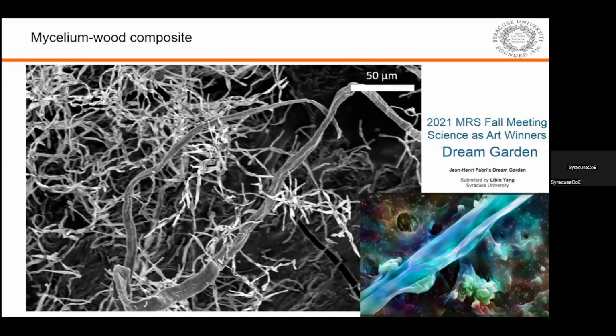And after we grow the mycelium on the petri dish, we put it together with wood fibers as the biomass. The wood fiber can be coconut fiber, or stalk or straw from corn after harvesting. We use a blender to convert those fibers into small pieces and grow mycelium together. Here's the microscopic image. The thin fibers are mycelium, and the thick fibers are the wood fibers. See, the mycelium not only attaches to the surface of the wood fiber, but also forms entanglement with the wood fiber. That's the way we believe the mycelium can play a role to bind wood fibers together, but also increase the stiffness and strength of the material.